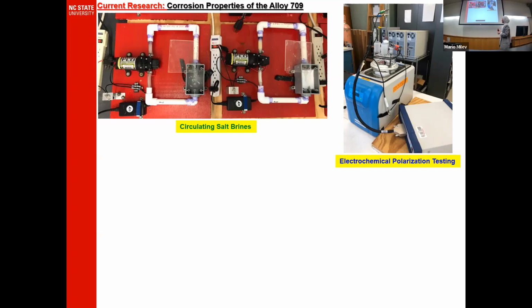The second test is the electrochemical polarization test, used to get corrosion rates versus temperature. We perform it at not high temperatures - 20, 40, 60, 80 degrees Celsius - because heat can come from decay inside the dry cask.